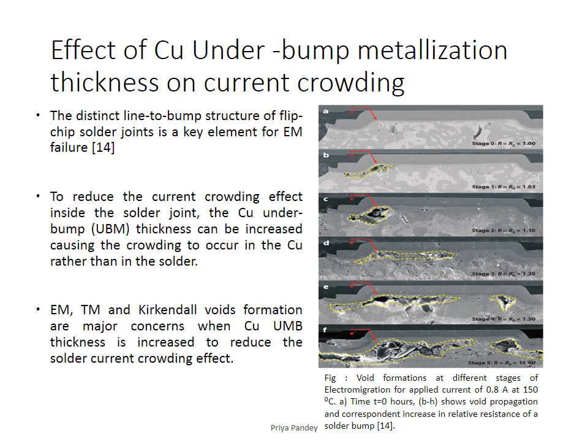Despite the nearly uniform current density, the void forms and grows larger with time at the current entrance of the bump. Furthermore, the void formation increases the Joule's heating, which induces a thermal gradient into the solder bump. Therefore, the EM, TM and Kirkendall void formations are major concerns when copper UBM thickness is increased to reduce the solder current crowding effect.